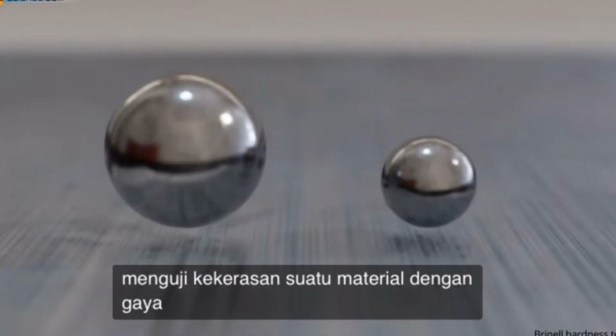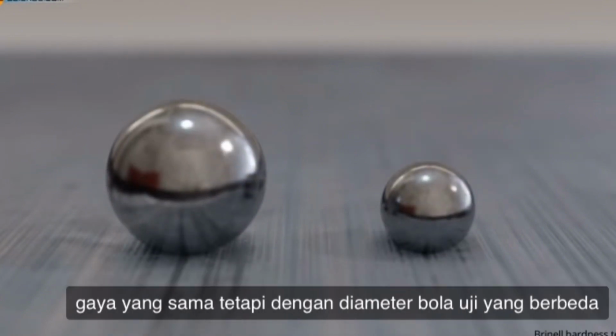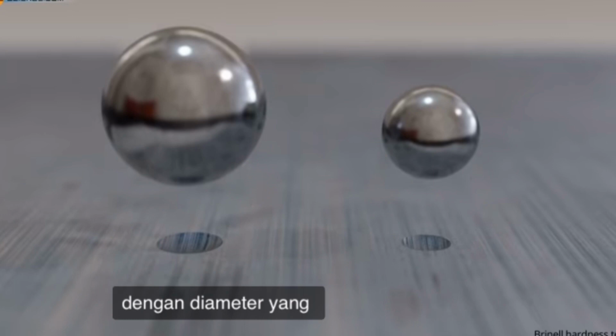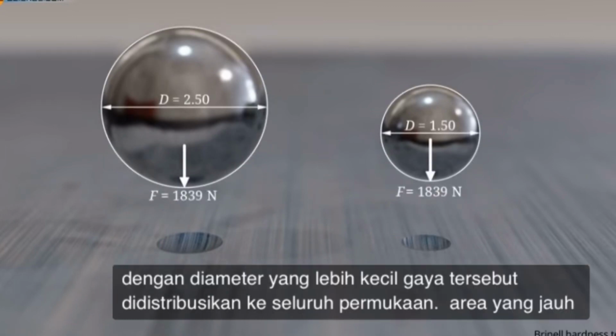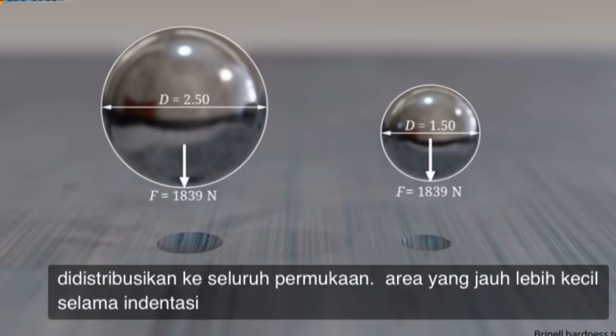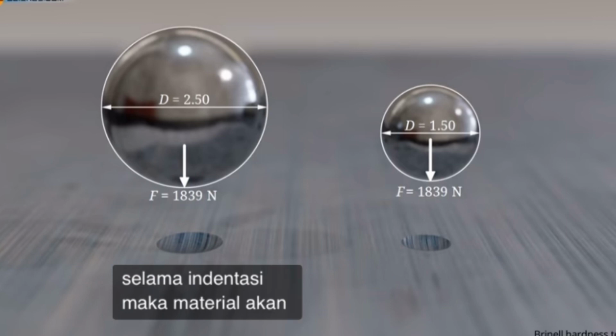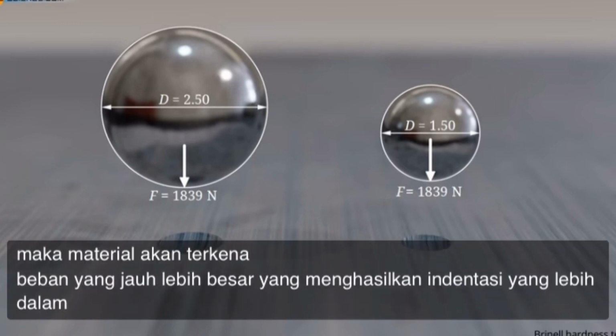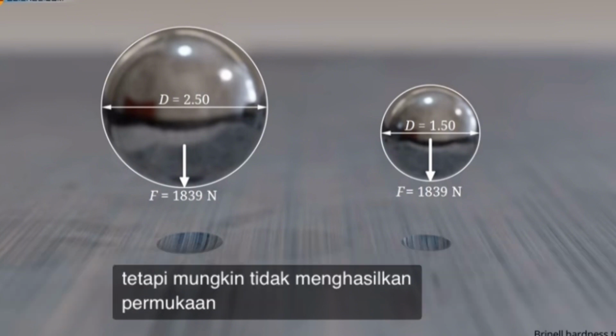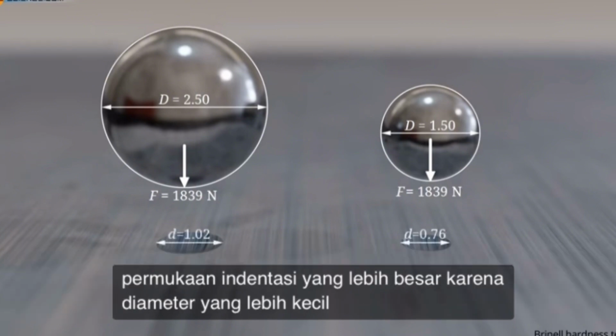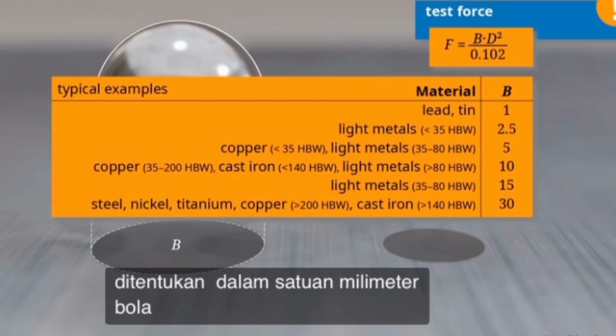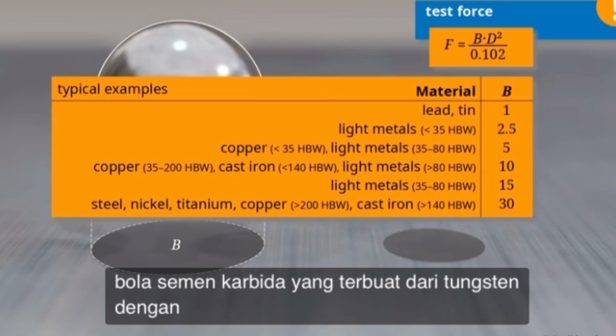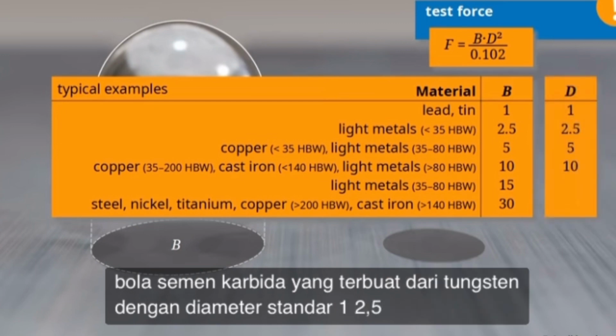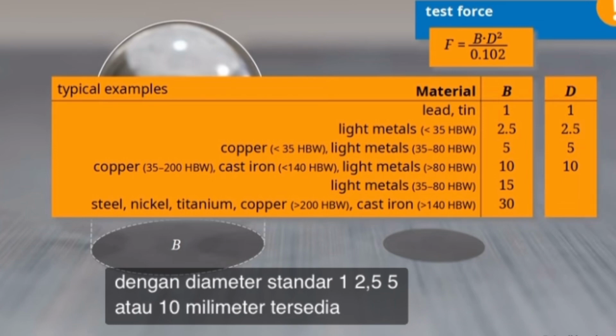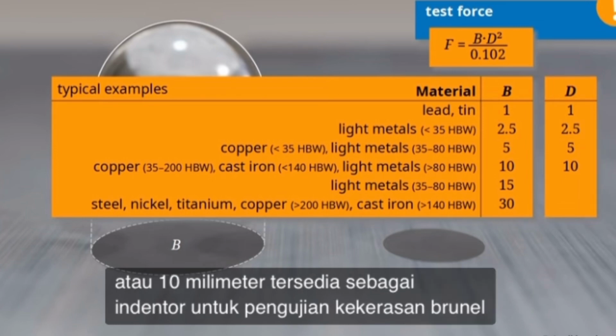Particular care must be taken when testing the hardness of a material with the same force but with different test ball diameters. With a smaller diameter, the force is distributed over a much smaller area during indentation. The material is thus subjected to a much greater load, which results in deeper indentation, but may not result in a larger indentation surface due to the smaller diameter. Cemented carbide balls made of tungsten with a standardized diameter of 1, 2.5, 5 or 10 mm are available as indenters for Brinell hardness testing.